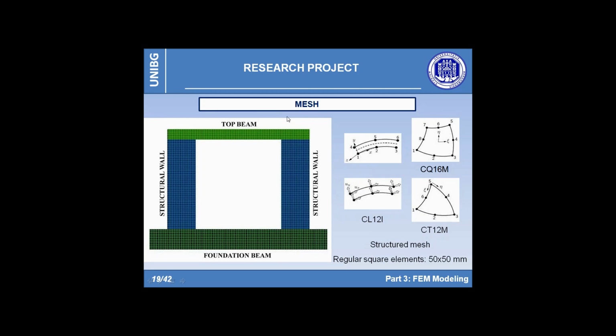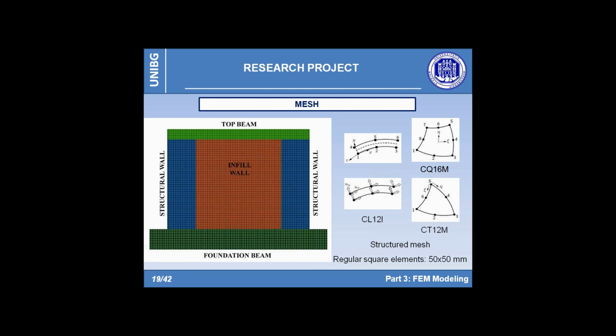The proposed numerical simulations are performed by means of two-dimensional models where all the geometrical parts are meshed using 8-node quadrilateral plane stress elements. The mesh shown in the figure is highly structured, regular, and with square elements having side equal to 50 millimeters. As shown in the picture, only for the last test, Wall 3, in order to smooth the edges of the window, 6-node triangular plane strain elements have been used, placing them in correspondence of the corner of the window to avoid numerical problems due to high stress localization.